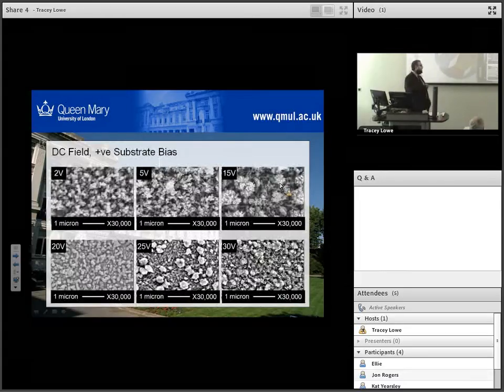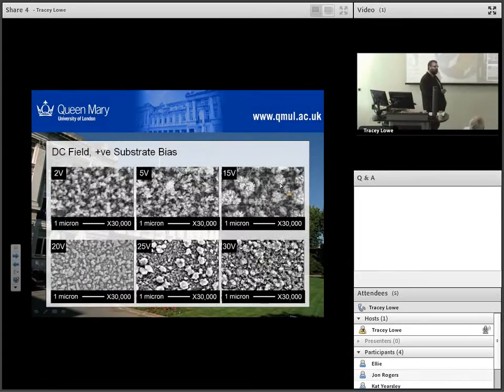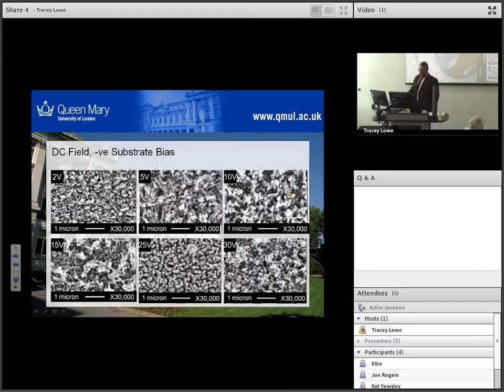Again, if we look at a fixed field, in this case positive substrate bias, we get certain morphologies, and at some point the growth mechanism changes and we see something else. Likewise, if we change the substrate bias, we see something different yet again, and again at some point we see a change in growth.